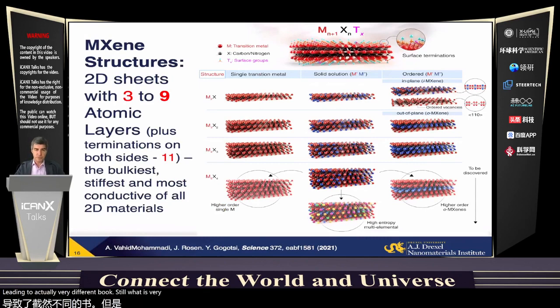Still, what is very important, and I will keep stressing this, we have an extremely large family of materials. We can have 2, 3, 4, 5 layers of transition metal, connected by 1, 2, 3, or 4 layers of X element, carbon, nitrogen, or their mix. And you will hear about oxygen soon as well. And they can have numerous surface terminations. Just do the math and you will easily come up with about 100 simple compositions. And if you add surface terminations, and about 10 have been already demonstrated, you will end up with 1,000 possible compositions. But it's possible to mix them, you remember, on the M side and X side. So we really have an infinite number of materials.